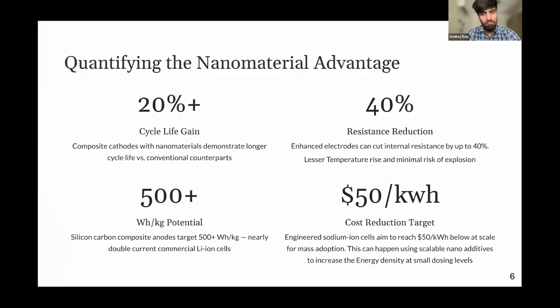So we need to aim right now for $50 per kilowatt hour. As of now, the LFP batteries have reached a good $100 to $90 per kilowatt hour figure, and it is going to come down with scale. As I was talking about, lead acid sits anywhere between say $30 to $40 and $60 for the premium chemistries out there. That's why lead acid is the most dominant and the most economical alternative as compared to lithium ion for applications where it can be replaced, not for applications like mobility and traction.